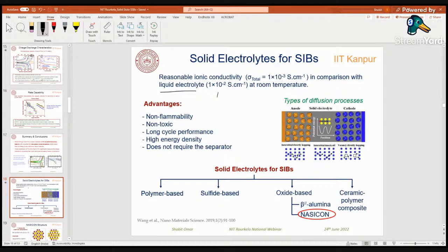The other one is the oxide base, which I'm going to talk about today. The first one is beta alumina, which has been known for a long time, and this beta alumina is also used for the high temperature sodium sulfur battery that operates at 300 degrees centigrade. Beta alumina is a very good sodium ion conductor. It can give you a conductivity of 2 millisiemens per centimeter. Please remember, this is 1 millisiemens. It can give you around 2 millisiemens per centimeter at room temperature.